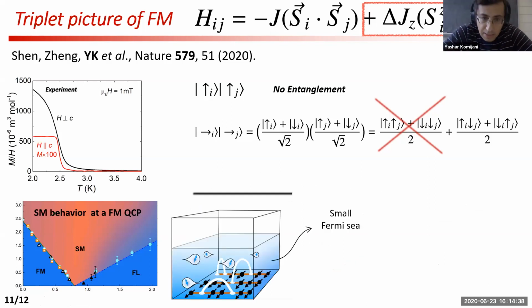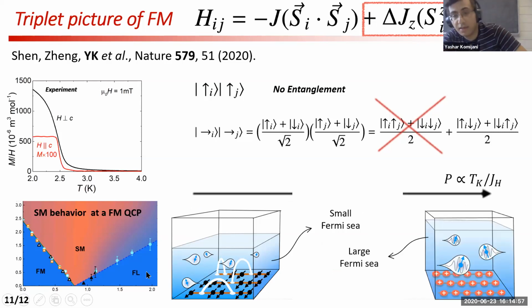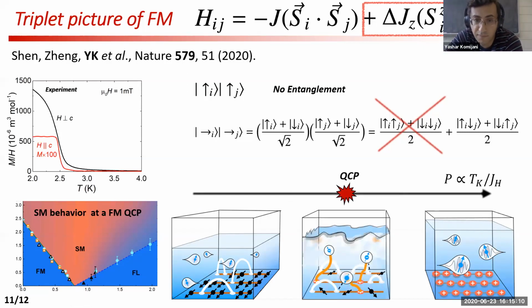So the picture that emerges for this phase diagram is that the ordered phase here is not a simple product state, but rather contains these triplet states, which may also be resonating. And on the other side, in the Fermi liquid side, of course these spinons have donated their electrons, and we are left with these positively charged holons and a larger Fermi surface. And in between, we have this soup of dangling bonds and everything fluctuating, right? Which is a mystery. We don't know much about it, and this would be responsible for this strange metal phase.